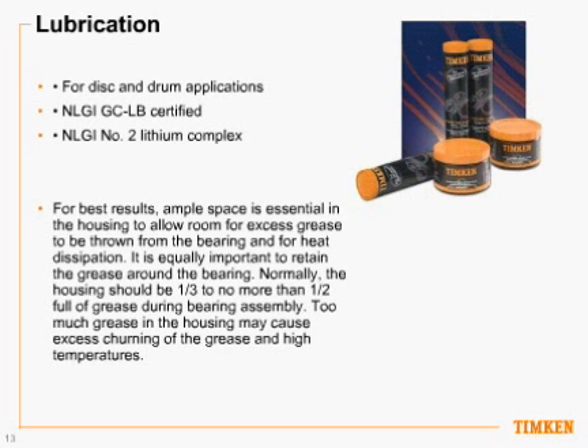Absolutely. It builds up heat. The lubricant and these materials all expand and contract with temperature changes. So by packing it full of grease, you're taking the airspace away, or the allowable room for it to expand and contract. And don't be surprised to see grease purging from the seal. A grease seal is made to purge or let off pressure buildup in the system, and if there's too much grease in there, it's just going to squirt the grease out.